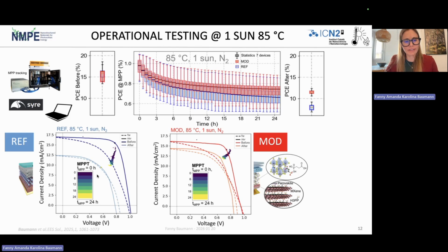And this becomes even clearer if we use our automated analysis that we built together with a Syre AI user interface system. We have very clear data for all of the cells that we have tested. In this case, it's 7 devices of each type. And we can really see that there's a characteristic decay. So it's a clear difference between the reference and the modification, with clearly the modification having another pathway towards the more degraded state, even though there's still some performance loss.